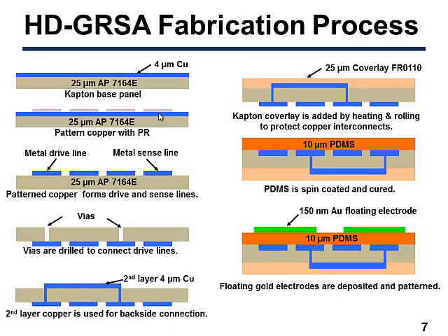We start with 25 micron Kapton with 4 micron copper. The copper is then patterned to form the sense and drive electrodes. Vias are drilled to connect with the drive electrode. A second layer of 4 micron copper is then added for backside interconnection. A 25 micron Kapton layer is then added by heating and rolling to protect the copper interconnect. One thing you need to notice is that during this step, the whole array will expand due to the heating and rolling, and this will cause a problem of photolithography alignment, which I will talk about later on.